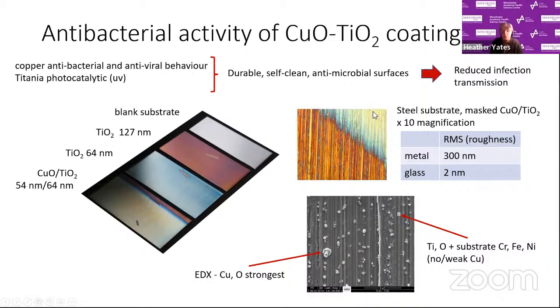The piece of metal I've got was masked. So the top blue bit is where the coating is and the bottom where it isn't. At the bottom, I've got a high resolution micrograph of the metal and the little lumps on it are the island growth from copper oxide. And in between, as shown by EDAX, you're getting the titanium coatings in between.